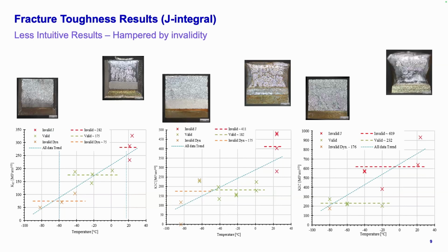Orangey color is also bad. That's where we've gone to dynamic invalidity. That's where the system hasn't come to a good equilibrium to be able to do the classic geometrical method. We get inertial effects, and it doesn't come to an equilibrium before the force can go down. So the most brittle ones, the coldest ones, are the ones that went dynamically invalid. They snapped before any good data could be extracted. So it's quite a small range that we can actually get valid toughness assessments coming out through these small tests.